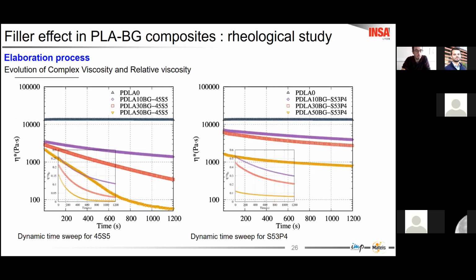So the dynamic time sweep presents a tool to observe the behavior of the nature and content at high temperatures. We can see that PLA at 150 degrees doesn't show any sign of degradation.